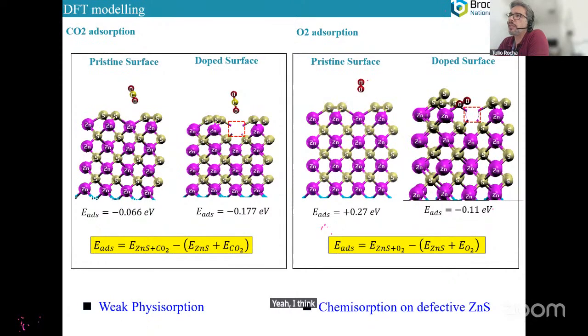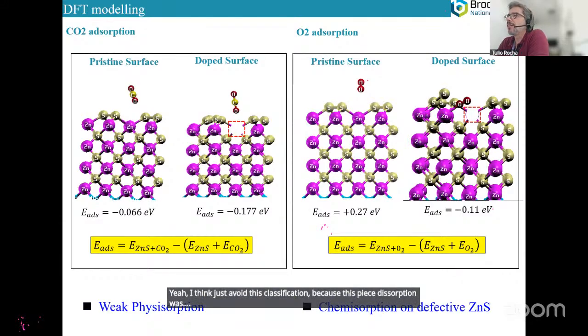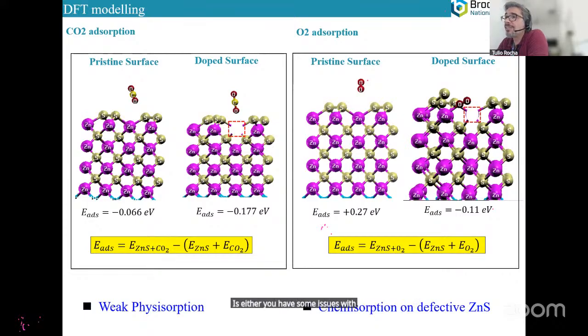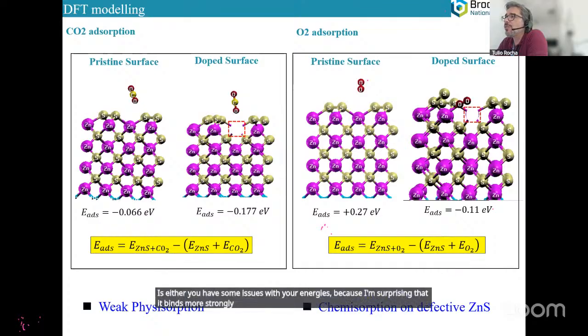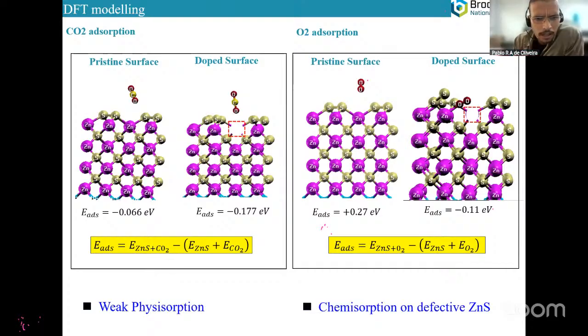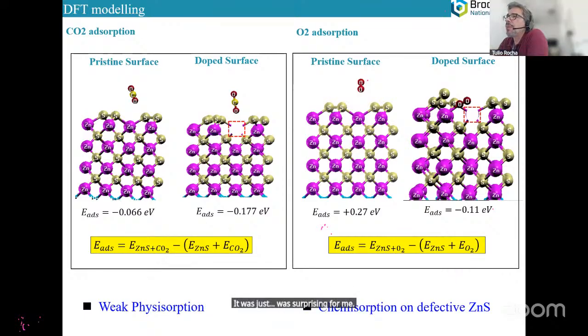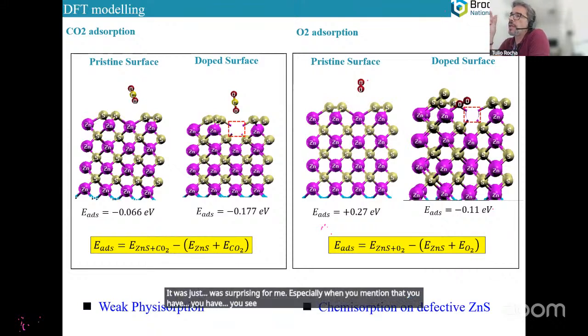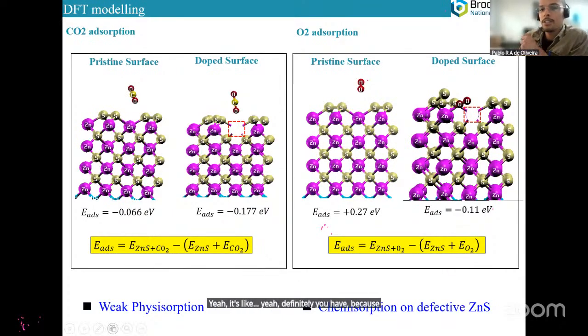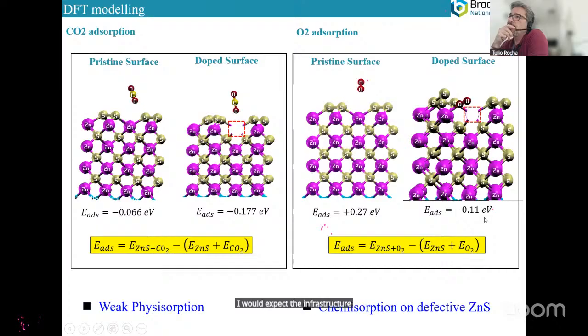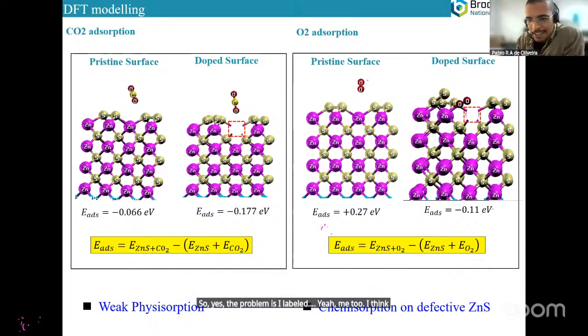Yeah, I think just avoid this classification, because either you have some issues with your energies, because I'm surprised that it binds CO2 more strongly than O2. I can double check the results. I'm not sure. I can double check my DFT calculations, but it was surprising for me, especially when you mentioned that it looks like the O2 molecule is stretched a little bit, so you most likely have charge transfer. Yeah, definitely, because this molecule has increased the bond length by, say, almost 10%. So it's most likely dissociating the oxygen bond. So yes, I would expect this to be much stronger than the CO2 on this defect, but yeah, me too. I have to check that. Yeah, definitely. I think the label is wrong. A typo. Yeah, exactly.